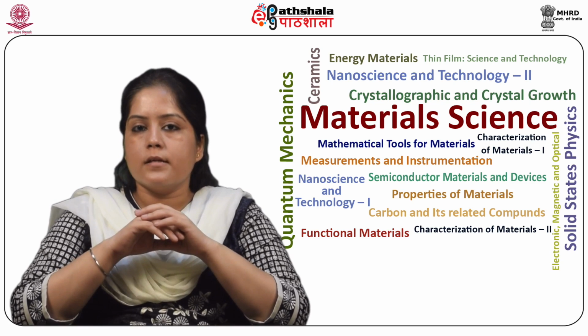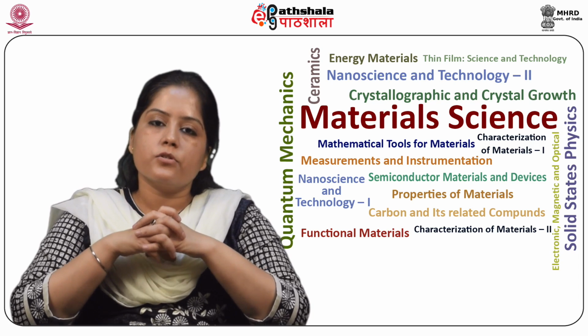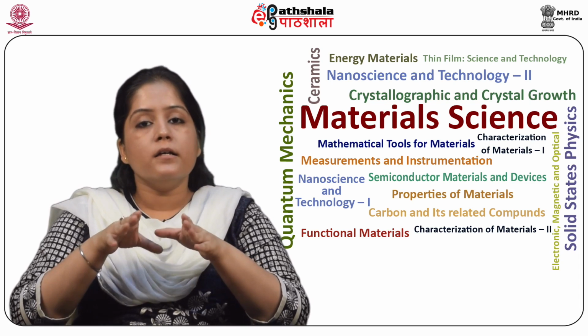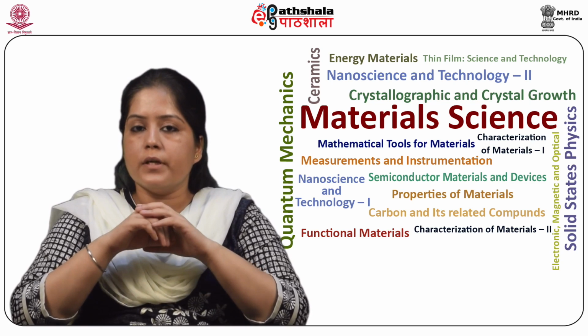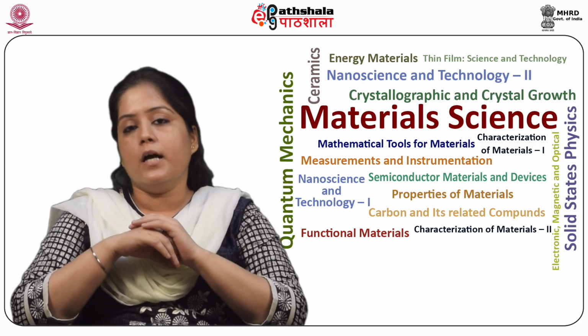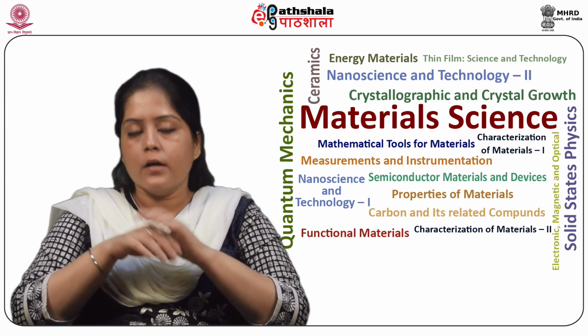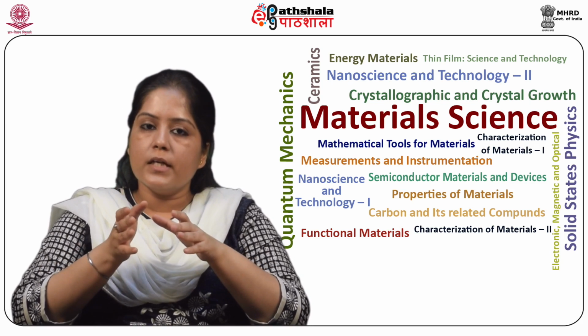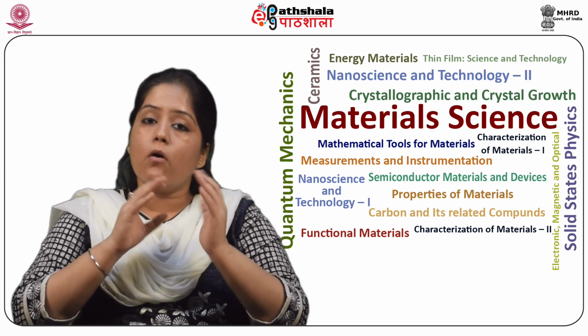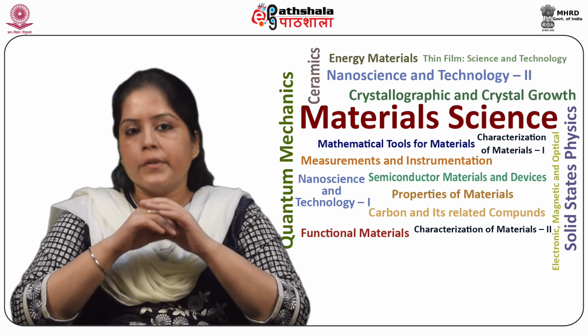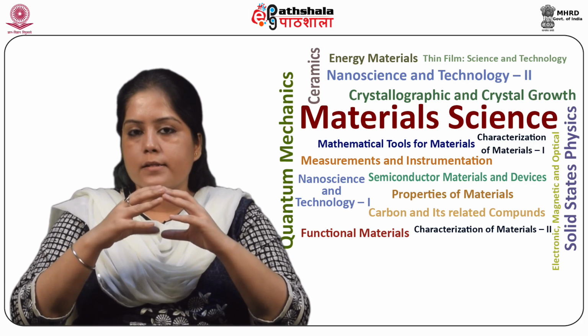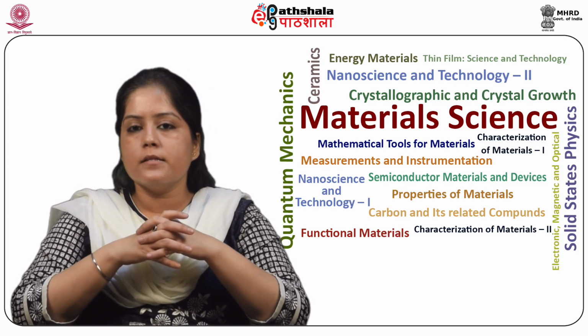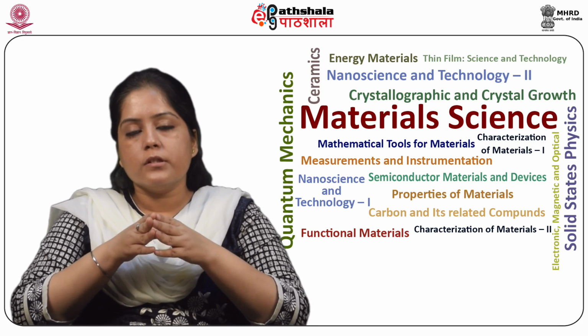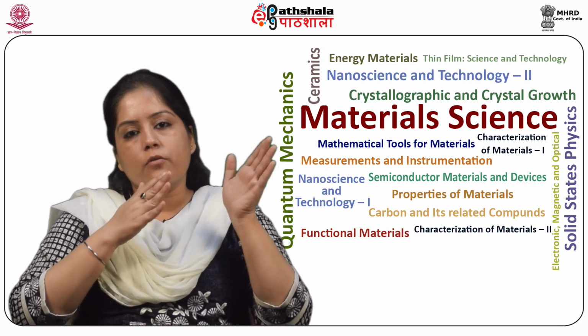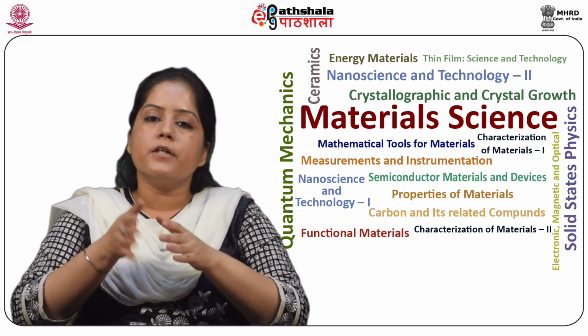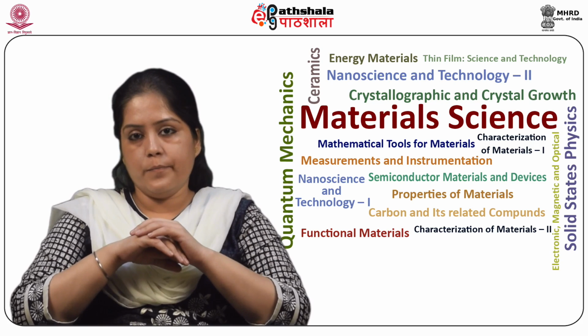So this results in a smaller electrostrictive coefficient, and students, note over here that they have large dielectric permittivities. So when an electric field was applied to the ordered perovskites, the smaller rattling space for B-site ions prevented the motion, resulting in the development of strain and further distorting the octahedron.